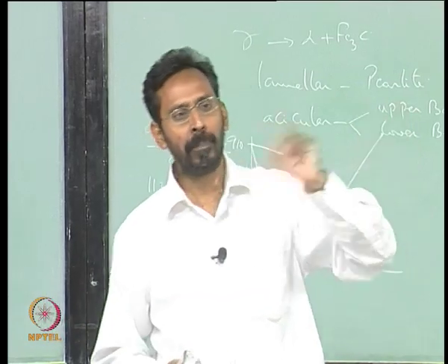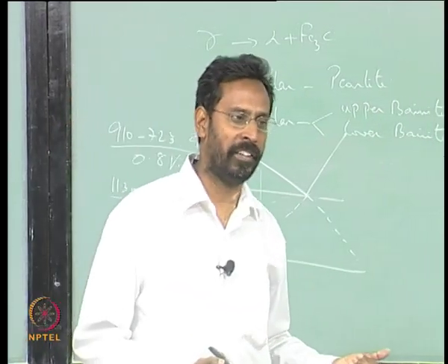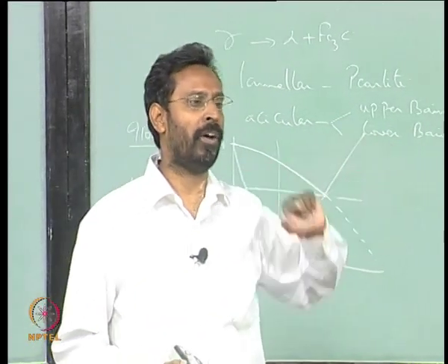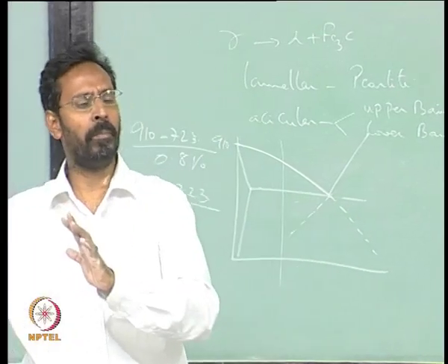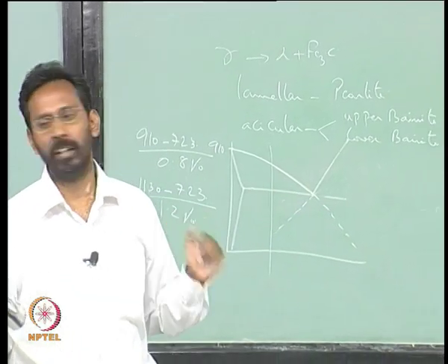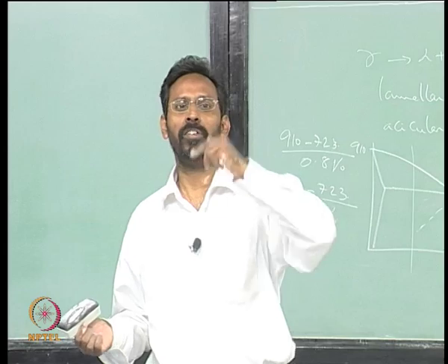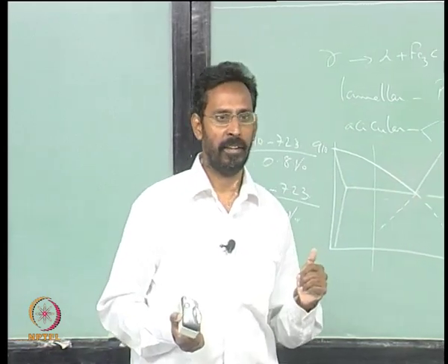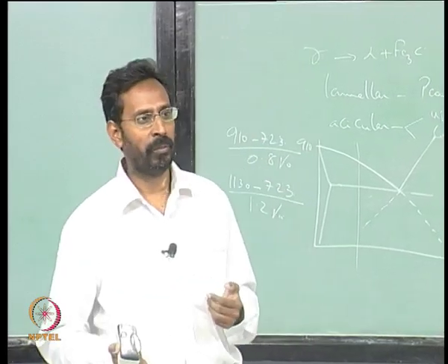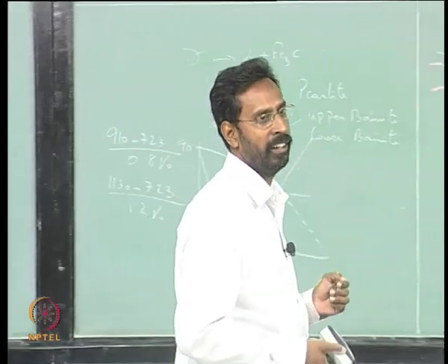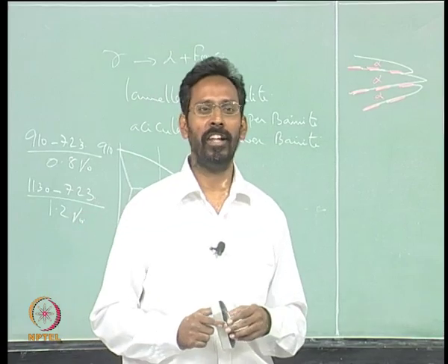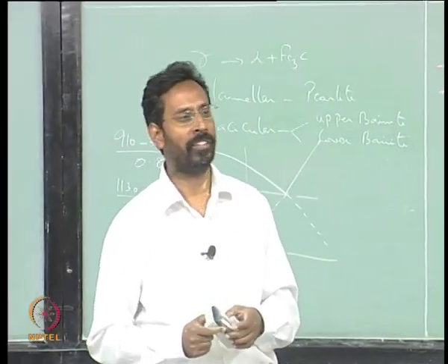Similarly here, if I can suppress the pearlite formation I can get the martensite, isn't it? So in order to get a martensite you need to suppress pearlite formation. So whatever methodologies that you can adopt to somehow suppress the pearlite formation is good for you. So one such methodology is increasing the grain size, but there are problems. What are the problems? Grain boundary oxidation, okay, fine. If I am doing my austenizing in a reduced atmosphere, you won't have the problem of oxidation,